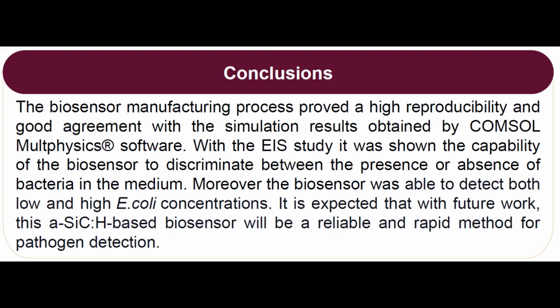The biosensor manufacturing process proved a high reproducibility and good agreement with the simulation results obtained by COMSOL Multiphysics software. With the EIS study, it was shown the capability of the biosensor to discriminate between the presence or absence of bacteria in the medium. Moreover, the biosensor was able to detect both low and high E. coli concentrations. It is expected that with future work, this hydrogenated amorphous silicon carbide-based biosensor will be a reliable and rapid method for pathogen detection. Thank you.